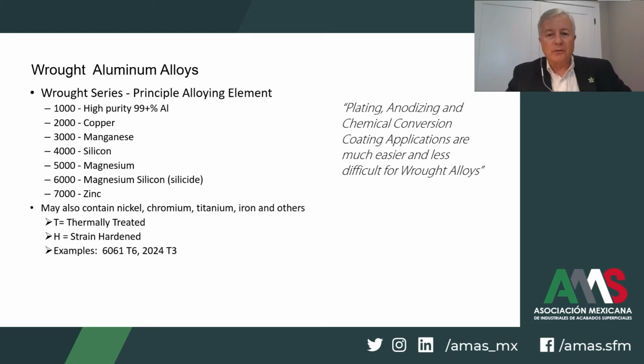You can see, in addition to aluminum, the primary alloy constituent in the highest concentration determines the type of alloy that's referenced. For example, by saying 2000 series, we see that it contains higher concentrations of copper. Or for a 5000 series alloy, high magnesium. Again, these metals provide a range of strength or other engineering performance properties that are important to the alloy. But all these different alloys have defined properties and uses for many applications. Generally speaking, the wrought alloys as shown are much easier to surface finish with plating or anodizing or even conversion coatings compared to cast alloys, which offer difficulty.